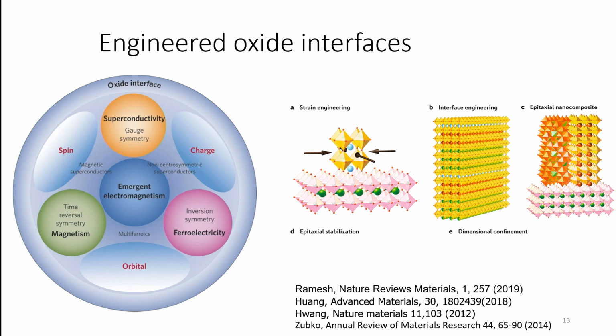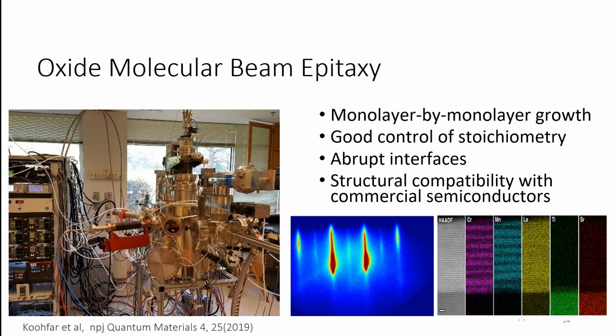So this is like Lego blocks. If you have kits with different Duplo Lego and Lego, they have very different sizes, and you cannot really push one on top of the other. But in this case, if they're close enough, one of them is going to stretch to fit the other template. So this allows us to change the structure of a material using this knob of epitaxial strain. And as I mentioned, we can also make heterostructures where we form interfaces and use the different interfaces we form as ways to tune the properties of these systems.